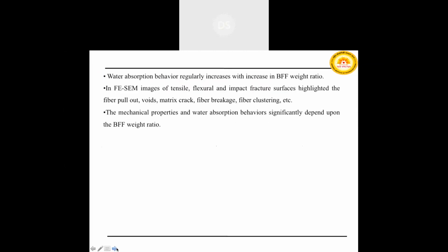The water absorption behavior regularly increases with the increase in Borassus fruit fiber weight percentage. FESEM images of the tensile fracture surface highlighted fiber pull-out, voids, matrix cracks, fiber breakage, fiber clustering, etc. And the last conclusion of this PPT: the mechanical properties and water absorption behavior significantly depend on the Borassus fruit fiber weight ratio. Thank you all.